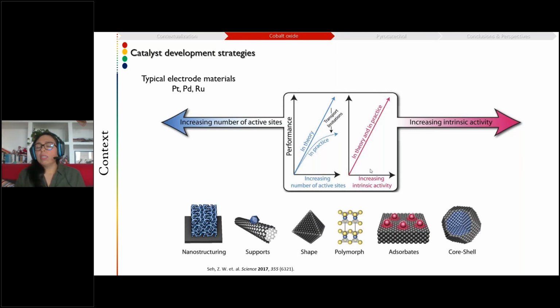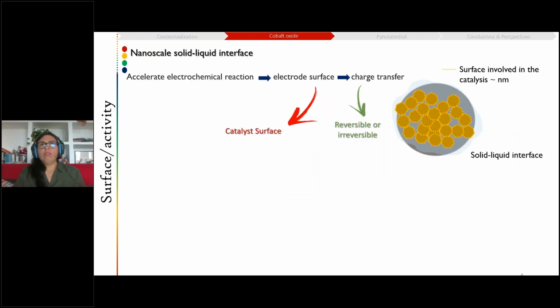And to do so, we need to understand what is the mechanism of electrocatalysis. And of course, if we want to understand this, we need to understand what type of process and where they take place. And actually, if we look at the electrocatalysis, it will take place at the surface of the electrode, but most importantly, at the surface of the catalyst. This surface is typically only a few nanometers thick. And we will need to understand also if these reactions are reversible or irreversible, because that might lead to degradation or deactivation processes. And more importantly, the interface at which this reaction happens is typically solid-liquid, because our materials are solid and our electrolytes are liquid in the case of fuel cells, for example.